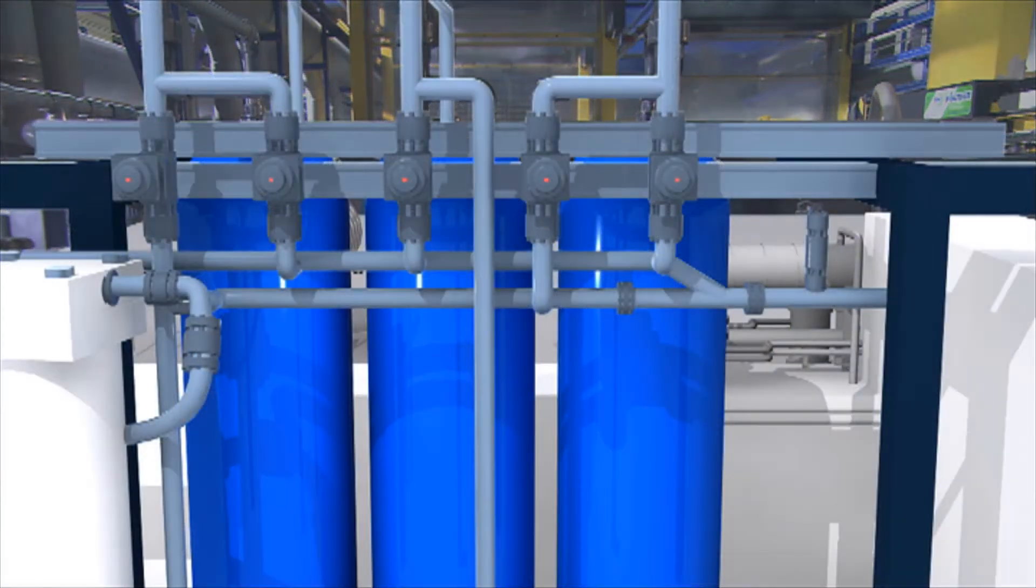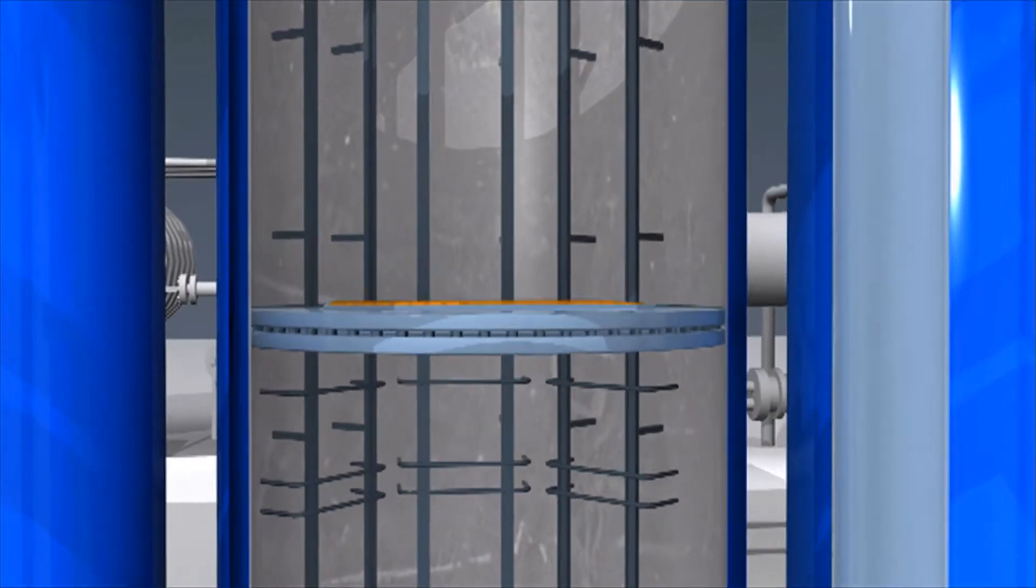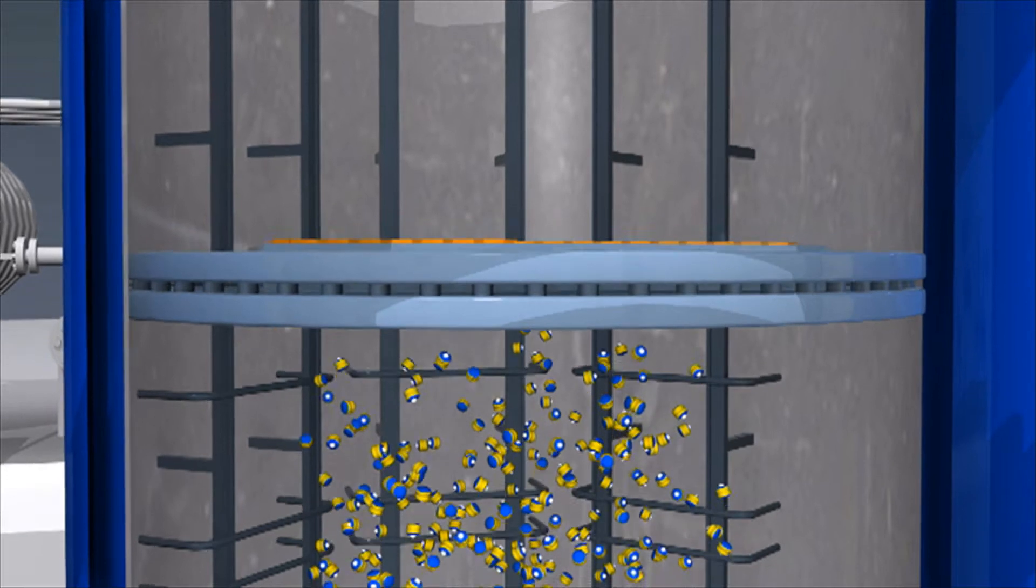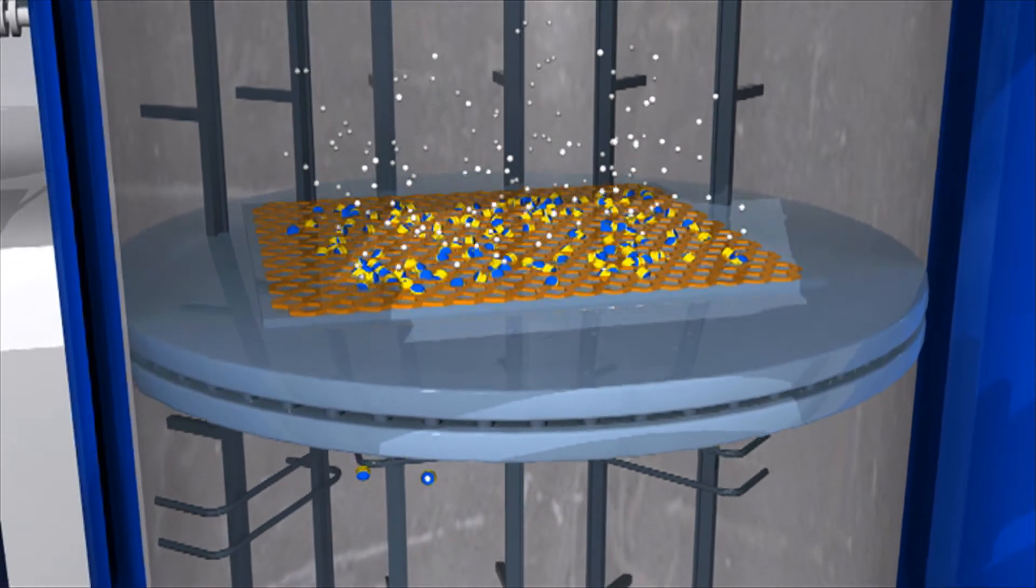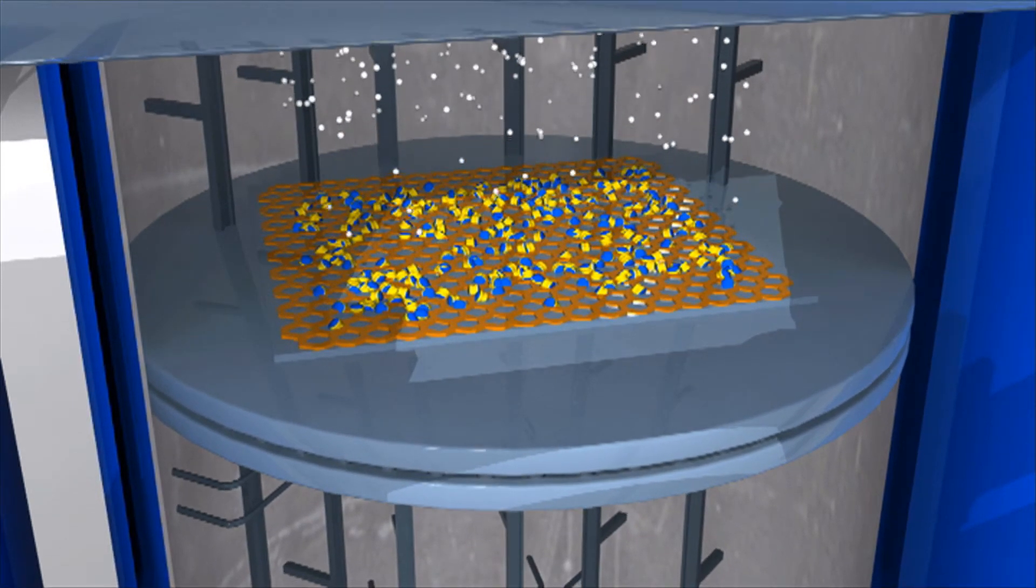In order to save resources and money, the Wetzlar company uses a special retardation process. Inside the unit, part of the anodization solution flows through a special resin, which draws back the sulfuric acid ions and allows the aluminum particles to move again.